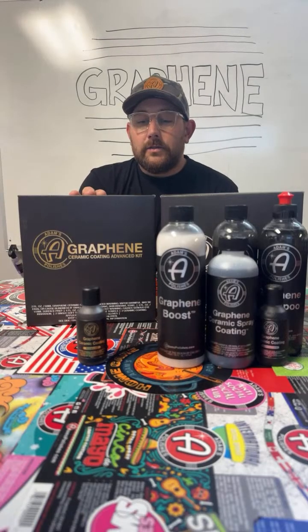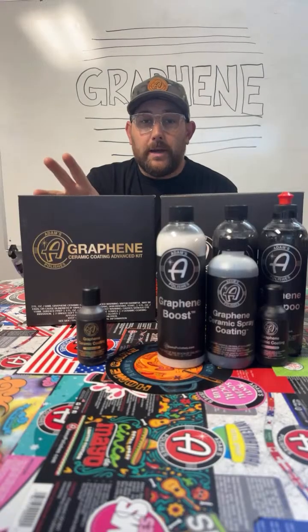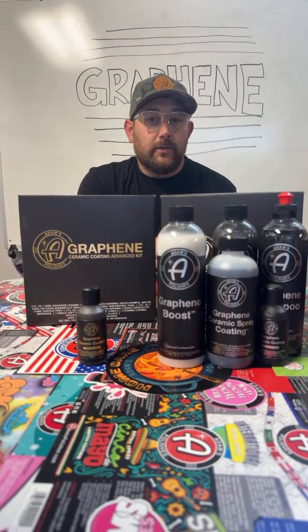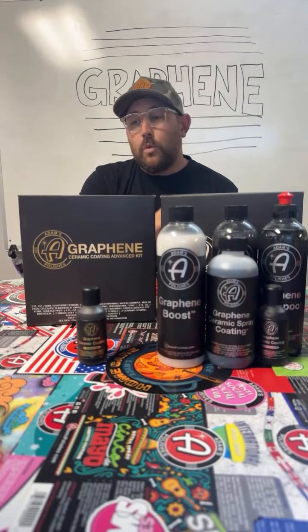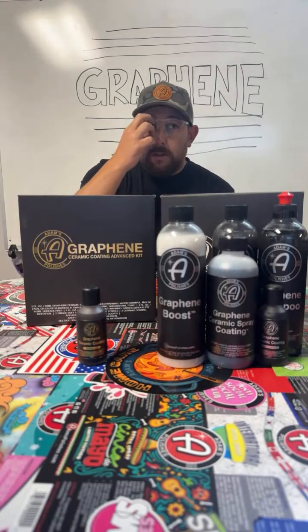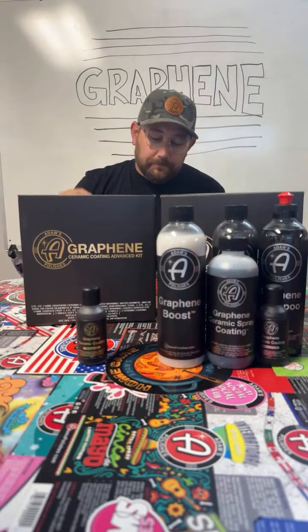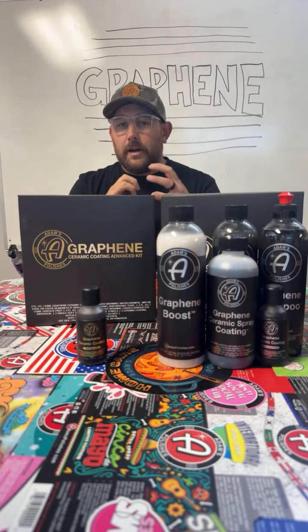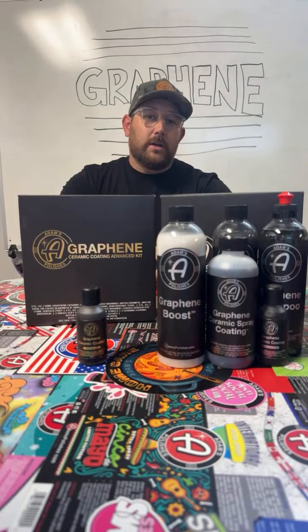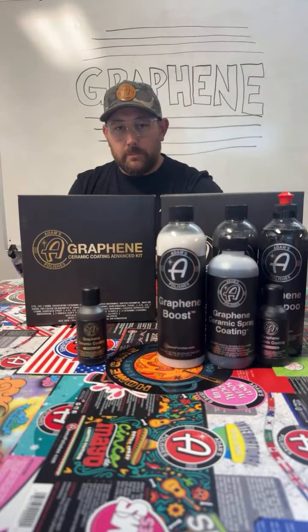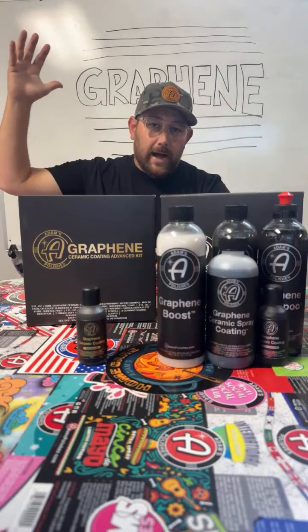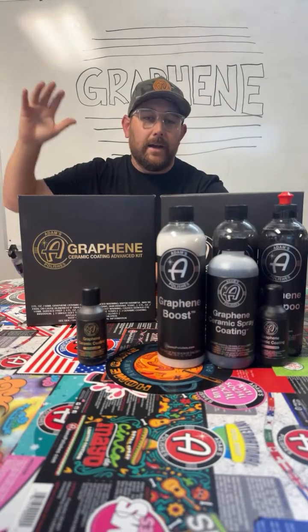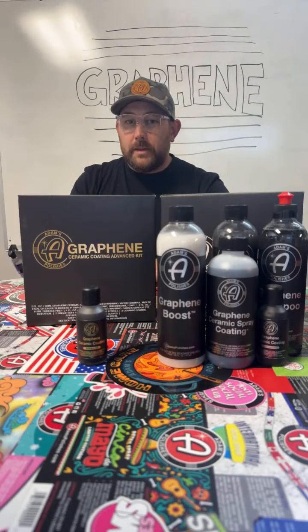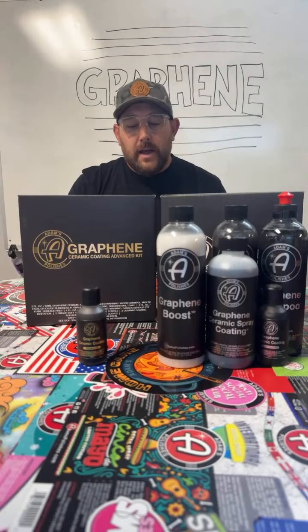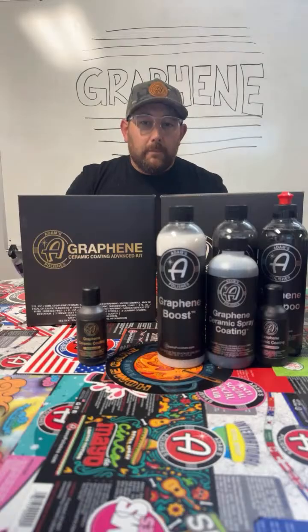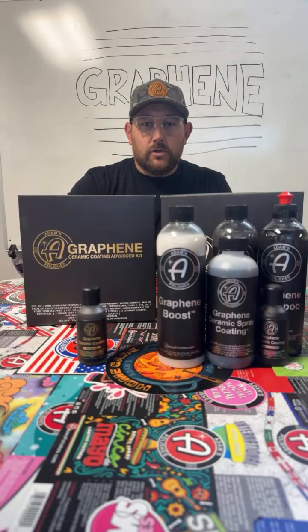And then Chris found a solvent manufacturer, and we switched to using a different solvent in our ceramic coatings, which made them way easier to work with. Realistically, when you apply a graphene ceramic coating, the solvent mixture with the reduced graphene oxide, the siloxane, and a bunch of other stuff goes from the glass bottle into your applicator and onto the car. The solvent starts to flash off the surface, leaving the graphene ceramic coating behind. The solvent is really the thing curing really fast. There's maybe a little bit of ceramic coating mixed in with that, but oftentimes the reason it's hard to wipe off is because the solvent has dried onto the surface.